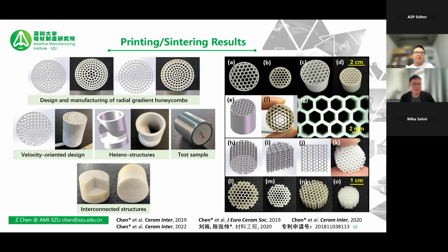For example, here I'm showing that if the velocity here is much, much higher than in the surrounding area, then we can put more channels, more porous structures here. So these are not the same as previous designs using conventional methods. Then after printing, we do the test. Some of the research is still ongoing. Then we are able to print many sorts of inhomogeneous structures, which are not possible with conventional technology.